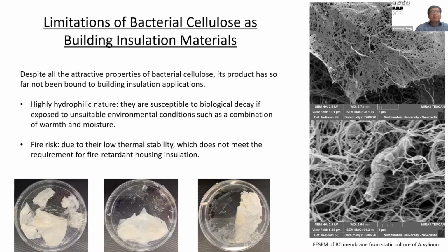But despite all of the attractive properties of the bacterial cellulose, its product has not been used for building insulation applications. There are several problems limiting their practical applications in the building environment. Firstly, the bacterial cellulose is highly hydrophilic in nature, resulting in very high liquid loading capacities. They easily decay biologically if exposed to unsuitable environmental conditions. The second issue of using bacterial cellulose as a source of insulation materials is the problem with fire due to their very low thermal stability.